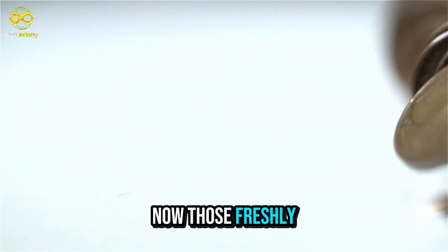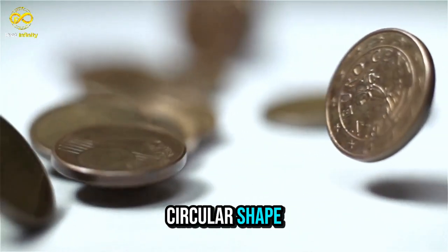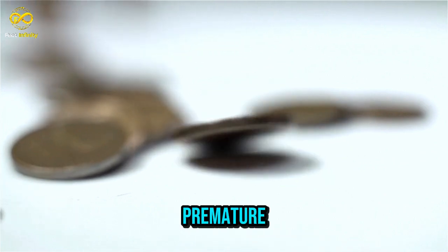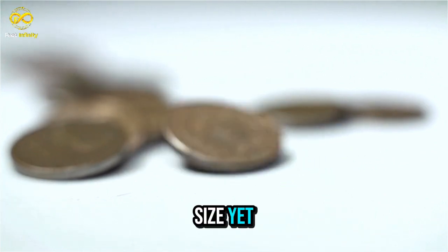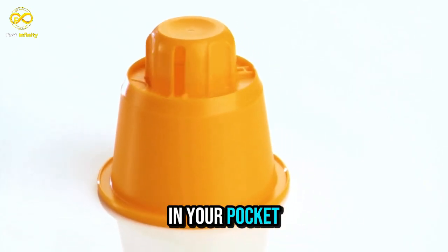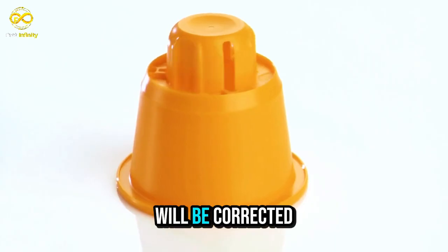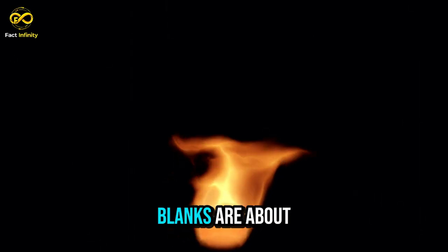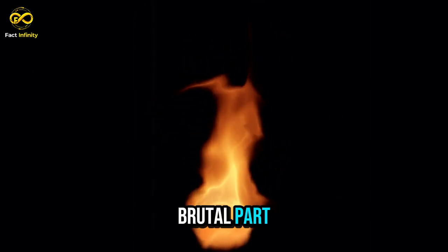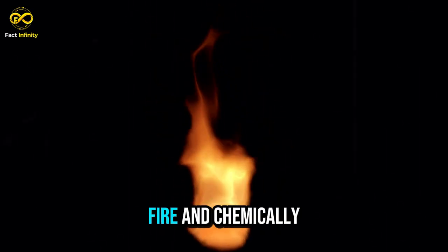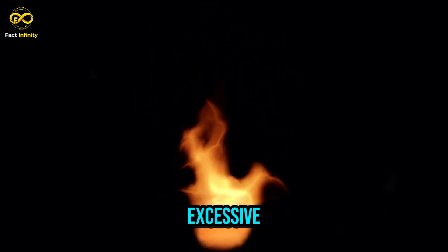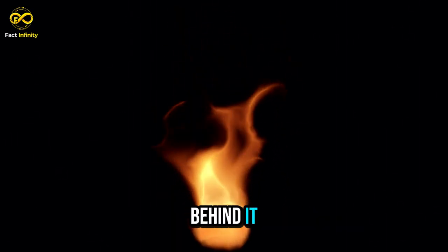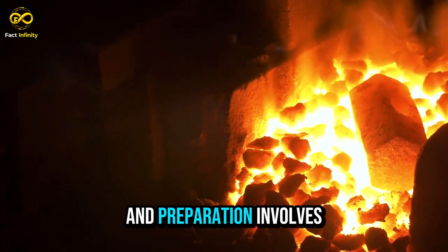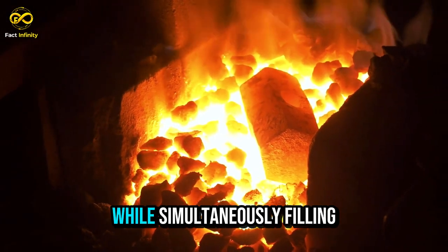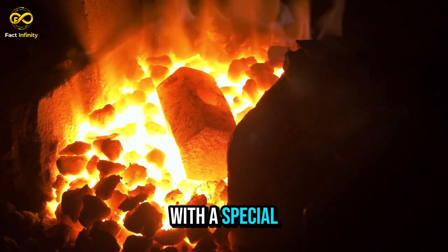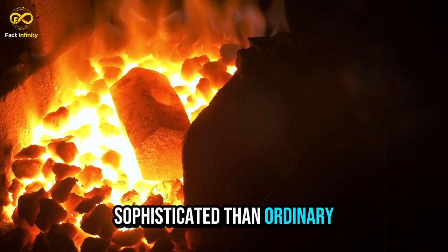Now, those freshly punched blanks have taken their basic circular shape, but calling them coins at this point would be premature because they're not quite the right size yet. The thickness matches what you'd find in your pocket, but the diameter is slightly off, a detail that will be corrected later in the process. For now, these blanks are about to embark on what might be the most brutal part of their entire transformation, a journey through fire and chemically treated water that would seem excessive if we didn't understand the metallurgical reasons behind it. The process is called annealing, and preparation involves firing up industrial furnaces while simultaneously filling massive tanks with a special liquid solution that's far more sophisticated than ordinary water.